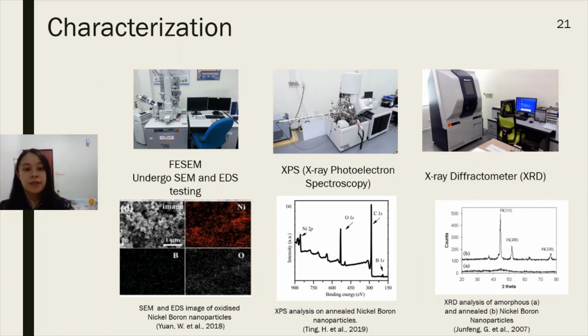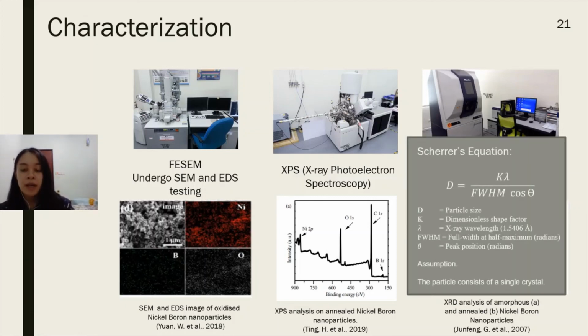So for the characterization, we will undergo SEM and EDS testing where we will study the morphology and also the presence of the elements on the surface of nickel-boron nanoparticles. For XPS, we'll study the chemical state of the nickel boride nanoparticles, while for XRD, we'll actually know the crystallinity of the nickel boride nanoparticles after being annealed at different temperature, and also we can identify the size of the nanoparticles through Scherrer's equation after using the assumption of each particles actually consists of a single crystal.